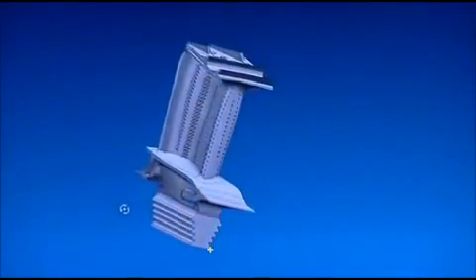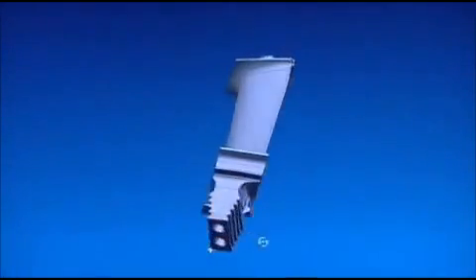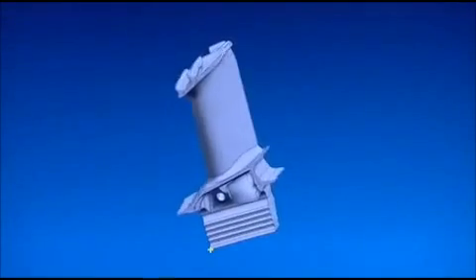The job these tiny blades have to do is unbelievably demanding. The blade exists in a fairly harsh environment — it has to rotate at about 10,000 revolutions per minute, at a blade speed of about 800 miles per hour. The component itself operates at something like 300 degrees above the melting point of the alloy. To operate at around 1,700 degrees, they're designed not to melt. Rolls-Royce designers used computer modelling to design a blade with a precise pattern of tiny air passages throughout.